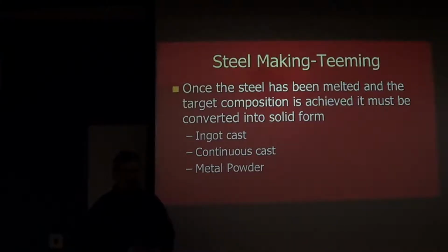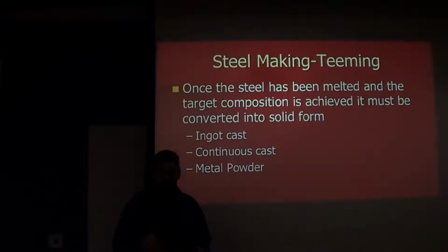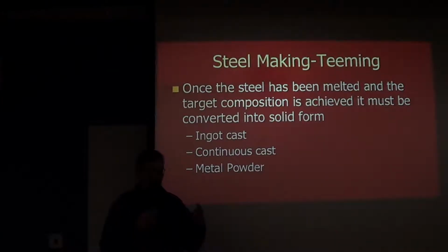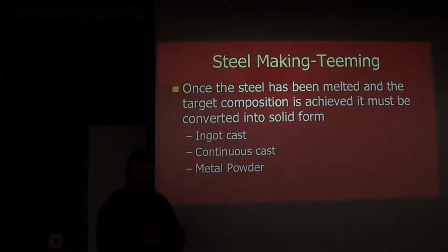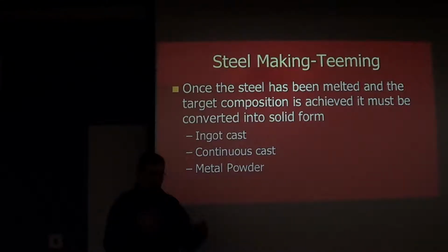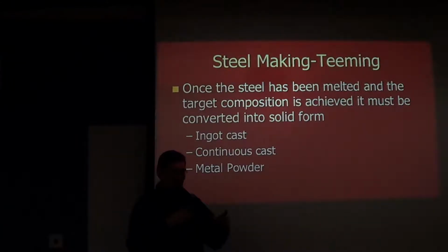The tundish can have different configurations and different numbers of openings. The mill that we deal with mostly uses a tundish that has 3 openings, so they can fill 3 molds at once. But the molds are not just big containers like a big ice cube tray. It's a bottomless mold that has a temporary bottom held in place with a hydraulic cylinder. You pour metal into the copper mold. The copper is water cooled, so it chills that metal on the outside pretty rapidly. And the hydraulic cylinder will lower at a slow rate, allowing that metal to continue to chill on the outside.